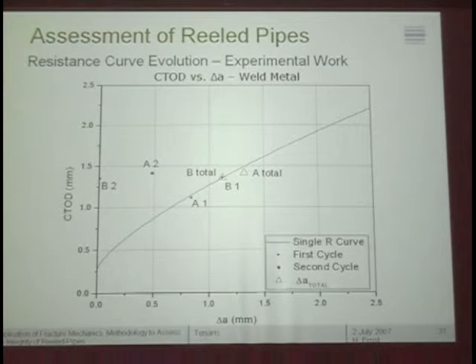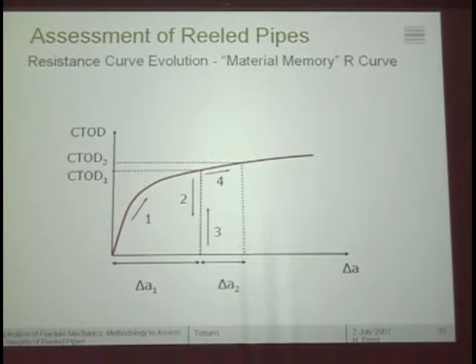And if you do that, this is what you have. This is the A total and this is the B total. In other words, as I said before, what we are doing here is precisely that. We are showing experimentally that this is what happens. If you have one CTOD at one level, you have some crack extension, you put another CTOD second cycle, the amount of crack extension is only this much. If I were to plot this much with this CTOD, I will have a point like here. But if I add the two together, I will put it on top of the resistance curve. So in other words, I can use the resistance curve with these rules to see how much crack extension I get in the first and second cycle.